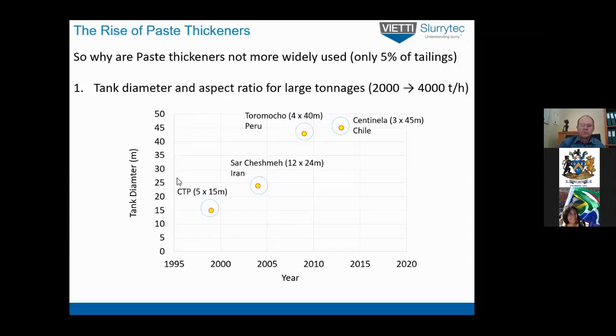So in the early days, before 2000, when CTP was designed and commissioned, the maximum diameter you could get for a deep cone paste thickener was about 15 meters. They were too scared to build them larger. Nobody had ever done that. So we were limited in terms of diameter and numbers of tanks we could get. Then the first big operation, Sarcheshmeh in Iran, was designed and built, and they could only get 24-meter diameter thickeners. So it had gone up from 15 to 24, and they got 12 24-meter paste thickeners in at that stage.